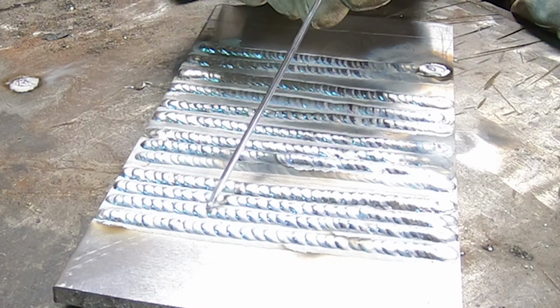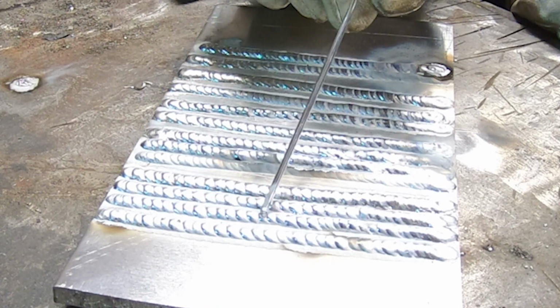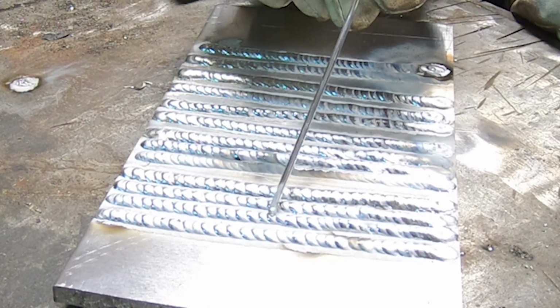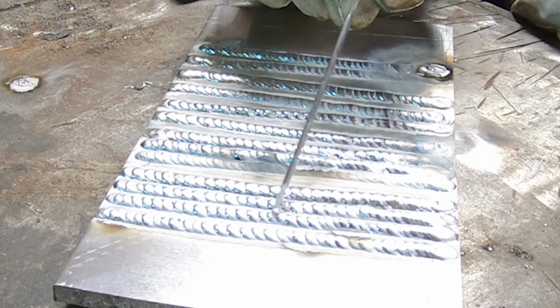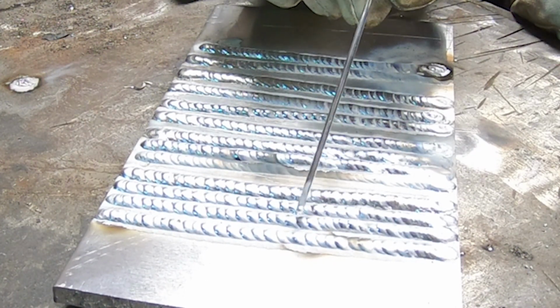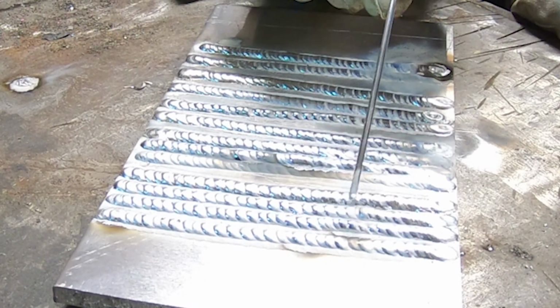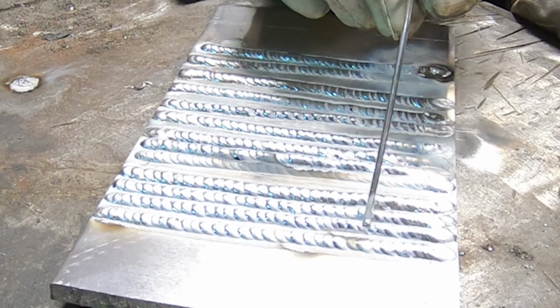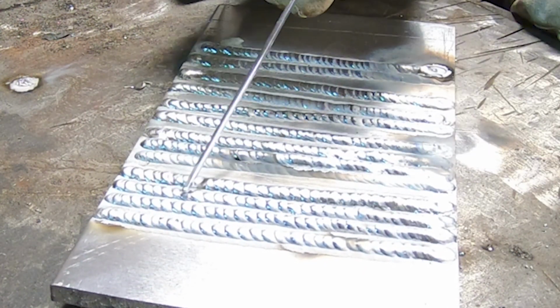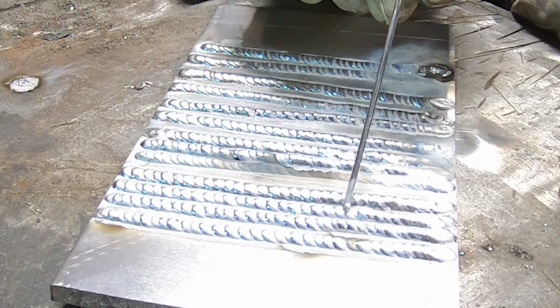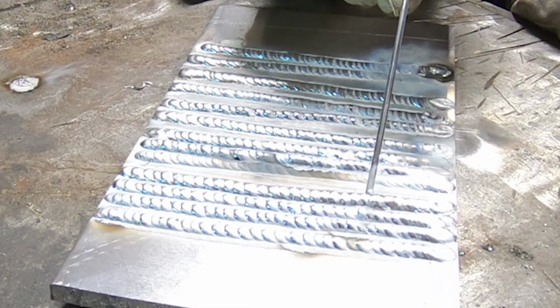We were doing pretty consistent dab wise until we got to here. Let off the pedal a little bit, the puddle skinnied up, and then we had some issue. Put power back into it, you can see the puddle widen, took power back out, and you see we really had a bad time over here. This bead wasn't doing too bad. It was pretty consistent all the way up until the point where I dipped the tungsten in the puddle.